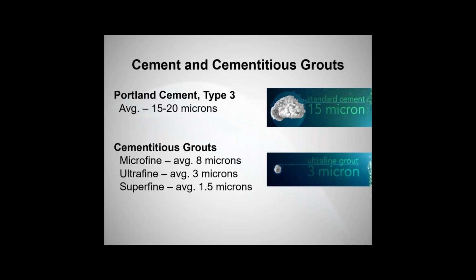So starting off with cement and cementitious grouts, to give an idea of the different scale of micron size, the average micron size for, let's say, a Portland cement type 3 is roughly 15 to 20 microns. And what distinguishes that from, let's say, a microfine or an ultrafine or a superfine is its particle size. Microfines typically on average have 8 micron particle sizes, whereas ultrafines are on average 3 microns. Superfines average 1.5 microns.